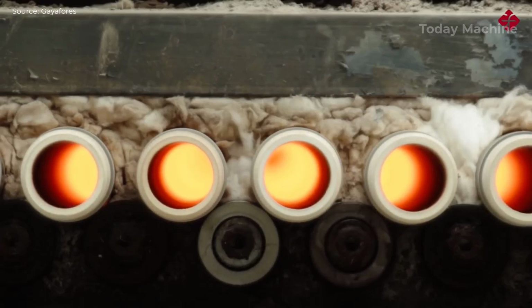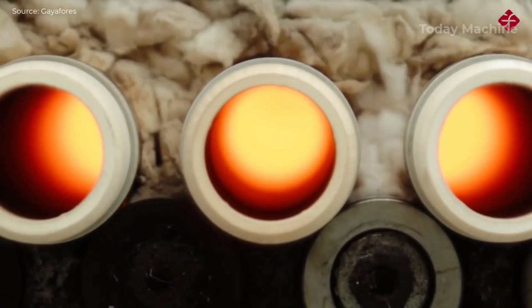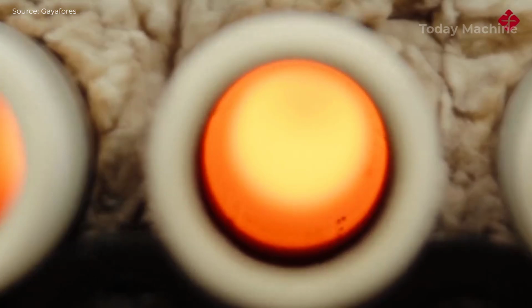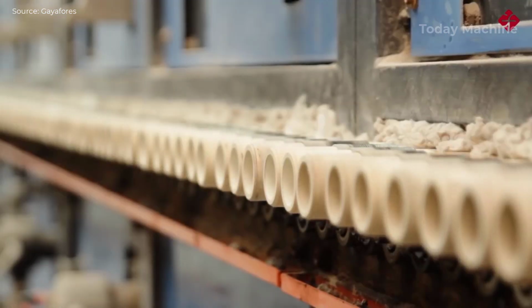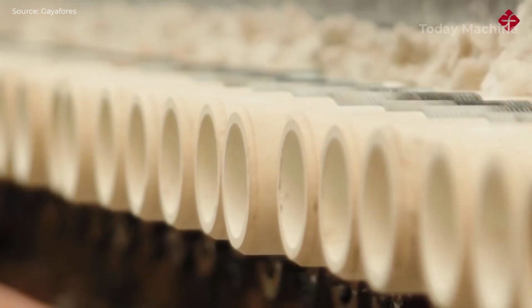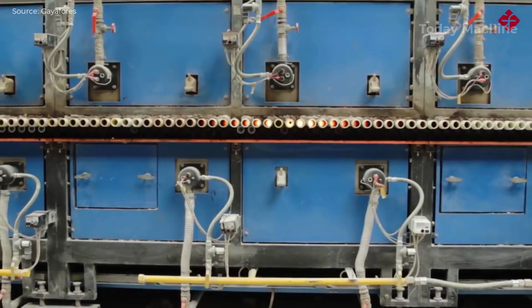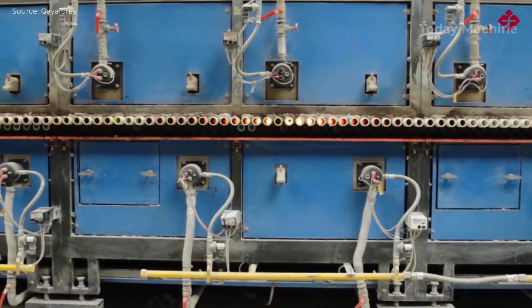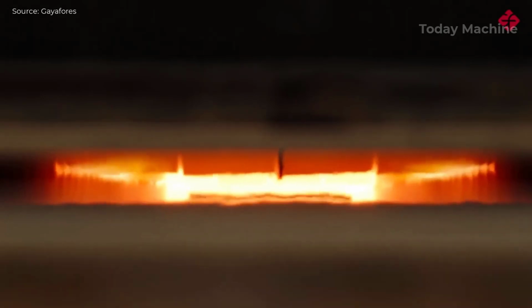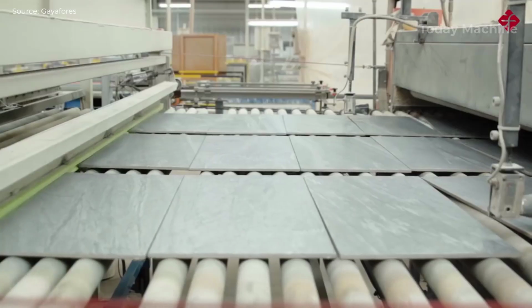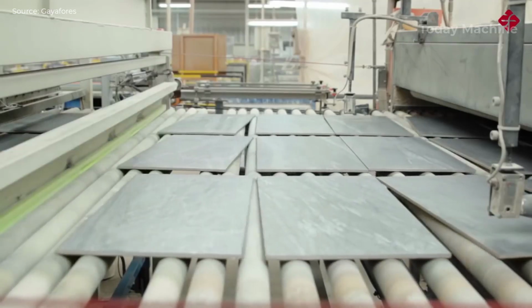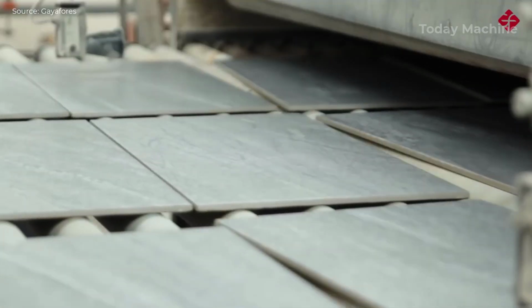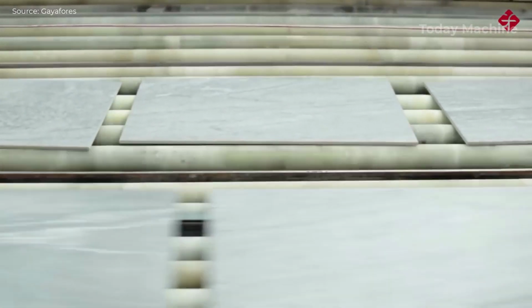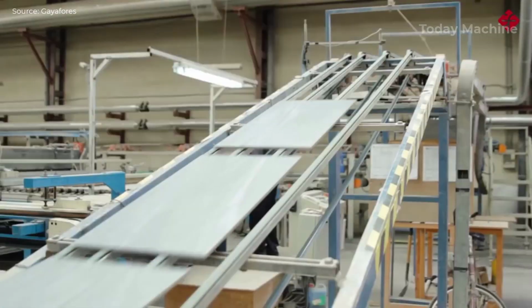The firing process occurs in a long kiln chamber, which is around 110 meters in length and 2.5 meters in width. The tiles are subjected to direct heat from the flame, which is efficiently managed to minimize fuel consumption. The kilns are designed to optimize heat recovery by reusing the hot gases produced during firing to preheat the tiles at earlier stages, resulting in energy efficiency. This rapid firing process enables Gayafores to produce a large quantity of high-quality tiles in a short period.